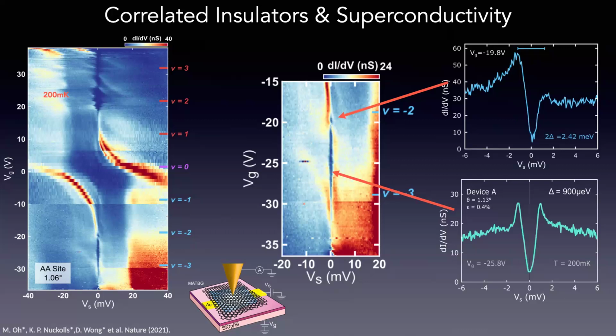I didn't include that in this talk, but we've done a lot of experiments in this regime of gating to show that this is actually a superconductor. The way we have done that is by using Andreev reflection with the same kind of device, where you push the tip into the sample and see that there are resonances which can be killed with magnetic field and temperature in this gate region. So this gap coexists with superconductivity, and this gap is not superconducting because there's no signal at these regions. I don't have the data here, but if you're interested, I can show it.